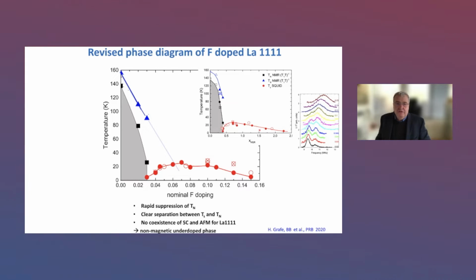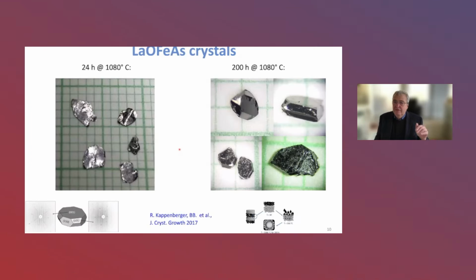So we are quite convinced that this phase diagram is really correct. So it's polycrystalline material, because the main problem with these 1111 type crystals, because we are not dealing with intermetallics, the main problem is to get nice single crystals where you can do reliable and sophisticated experimental studies. And at least for these parent compounds, we had a breakthrough, and that is a couple of years ago.